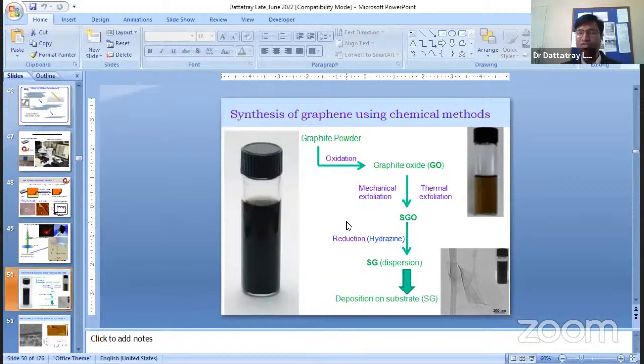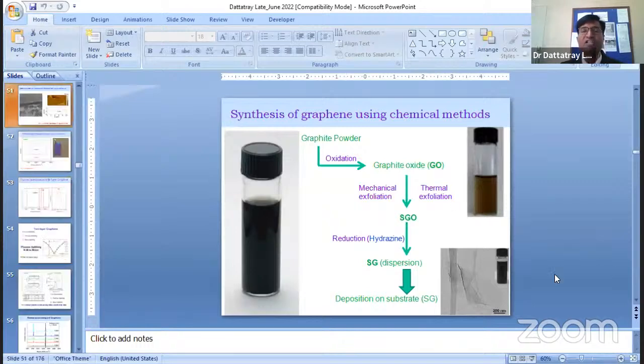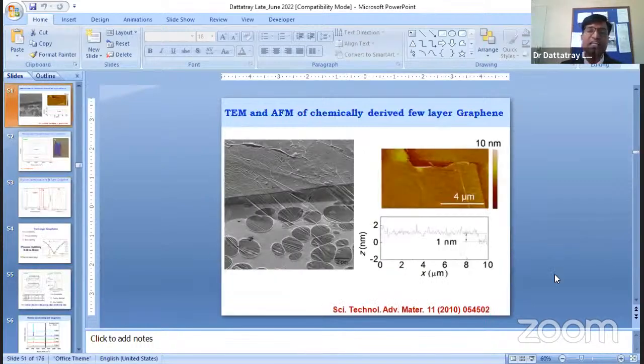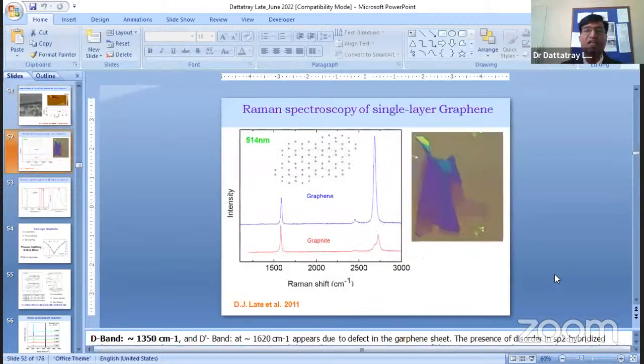And for technological applications, any kind of sensor application, you can drop cast, or you can do any coating, dip coating or whatever coating you want, depending upon the kind of application you choose. Of course, you can do TEM and AFM, and measure the thickness of the grown material or grown graphene. And of course, one of the very powerful techniques to identify whether grown or transferred graphene is 1-layer, 2-layer, or multi-layer is Raman spectroscopy.